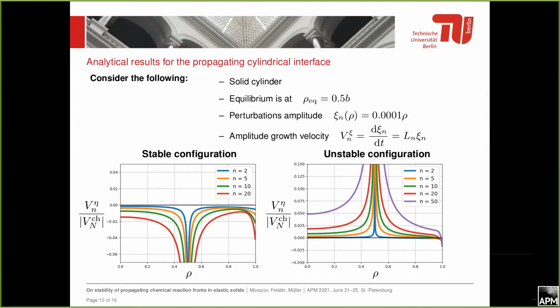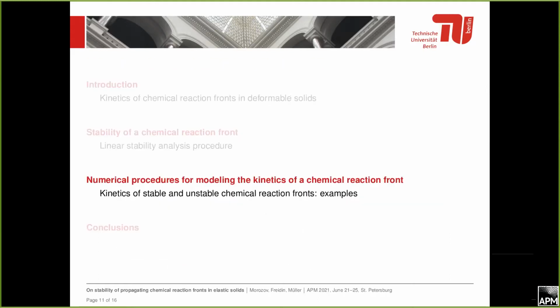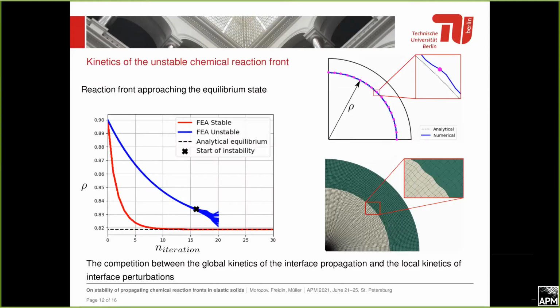For every position of the interface, we see that it's stable not only at equilibrium, but all the way to the equilibrium, and vice versa for an unstable configuration. And in the last 2 slides, I want to show you what we have seen in our numerical experiments. If we consider, for example, an initially perfectly circular interface propagating towards some equilibrium position, we see that in case of a stable configuration, all points of the interface smoothly converge to the equilibrium position.